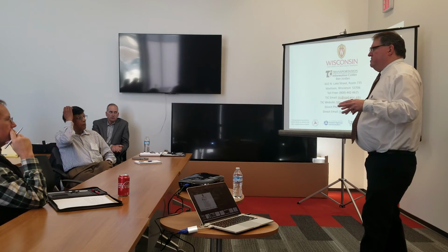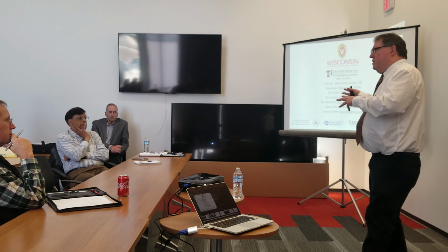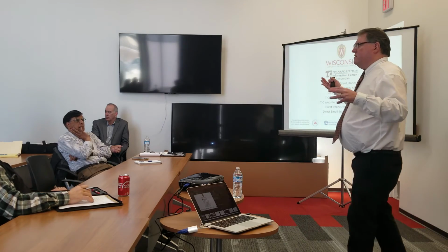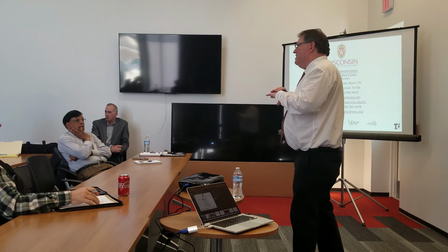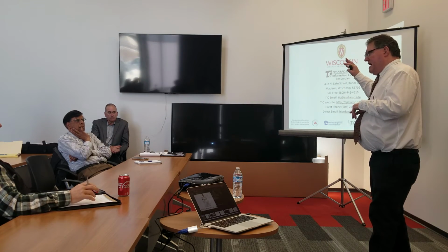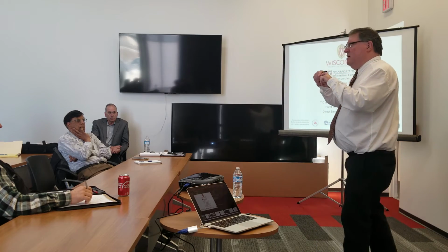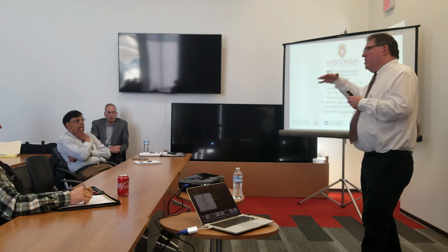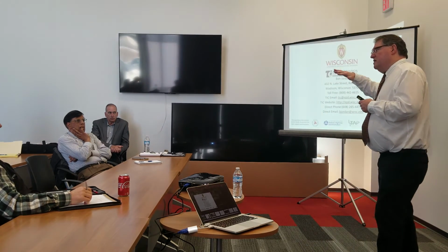What I would do now is look at my chip seal process and try to identify, do we have deficiencies in our spec, in our material, in our workmanship, that we can correct to get that to perform better. So I'd be looking at polymer modified emulsion, something like a CRS-2P, making sure I have good cubical stone, single size, with as little dust as possible, okay? And making sure the application is done appropriately, the mix design is correct so I have enough liquid asphalt to hold that stone in, and that I'm not applying excess stone. I'd look at all that performance stuff, make sure I have that right, and then see if I could run a chip seal program that didn't get all the neighbors upset. And if I can't do that, then I would look at the other options.